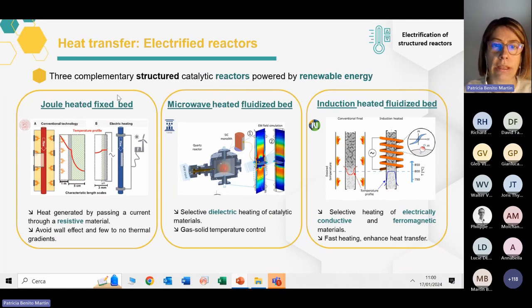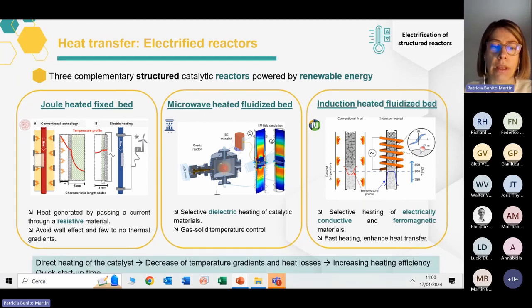We have dual microwave and induction heating. So we will generate the heat by passing a current through a resistive material, by the selective dielectric heating of catalytic materials, or by the selective heating of ferromagnetic materials. So we have 3 different ways of heating, but we chose all of them because they show common advantages. Our aim is to directly heat the catalyst in order to decrease the temperature gradients and heat losses, and in the end increase the heating efficiency, and all of this with a quick startup time.